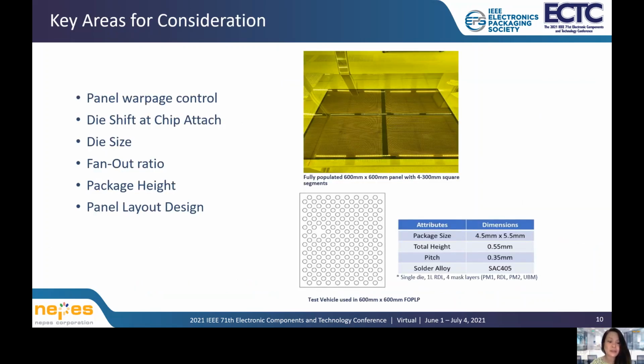Successful processing of 600 mm PLP hinges on several factors. However, panel warpage control is the primary factor driven by die size, fan-out ratio, package height, and panel layout design. For our evaluation, we took a look at a test vehicle with 4.5 by 5.5 millimeter package size. This is a single die with one layer RDL with 350 micron ball pitch, 0.55 millimeter total package height, and solder alloy used is SAC405.